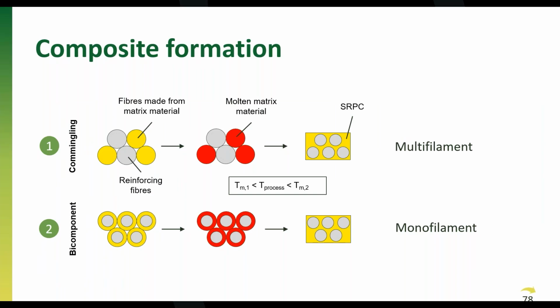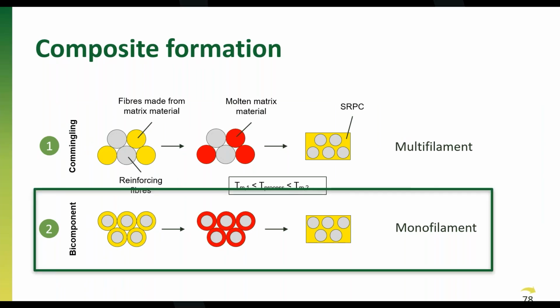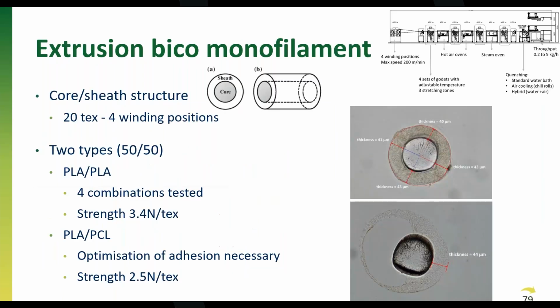For the bicomponent route, it's a little bit different because in this case, each reinforcement yarn already has a core sheath structure. So in the core, the reinforcement, and in the sheath, the matrix yarn. So each reinforcement yarn already contains the matrix. And then again, the same process is used with pressure and temperature in between both melting temperatures. First, some more details on the production of the bicomponent yarns, in this case a monofilament extrusion line, because our multifilament extrusion line cannot handle bicomponent yarns. We focused on the core sheath structure. In the core, of course, the high melting, in the sheath, the low melting material.